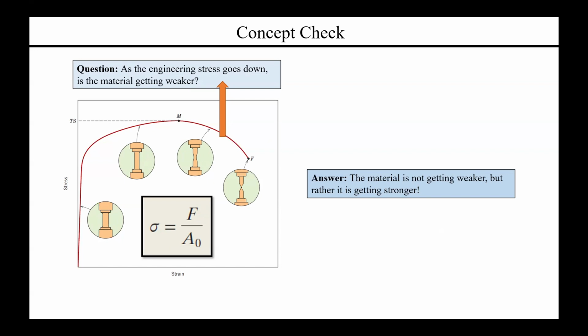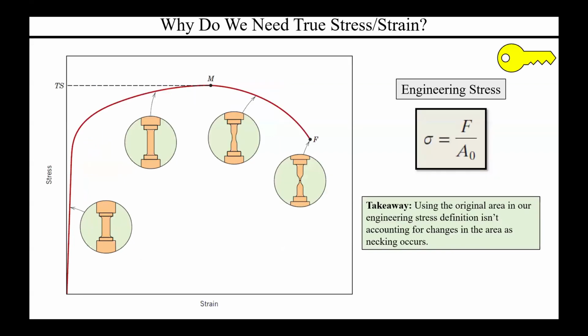But as that area, specifically that cross section, is changing, and it changes significantly after the tensile strength point. In fact, it's not even potentially the same shape anymore, right? Once you have this necking region, you have this very complex topology that could be happening within that failure zone. So the area is nothing compared to what it was in the beginning. So what is potentially happening is that the stress-strain relationship with respect to the initial area could potentially be significantly underestimating the amount of stress that would actually be needed to further strain the material.